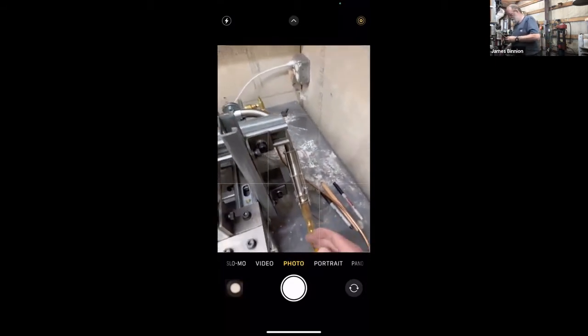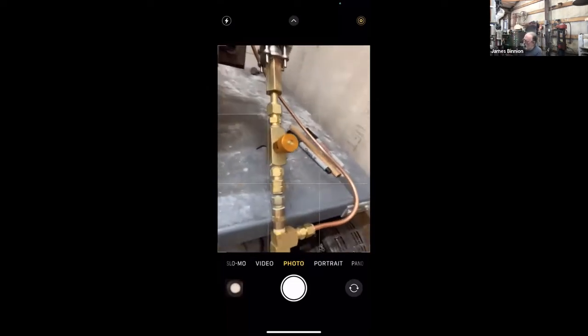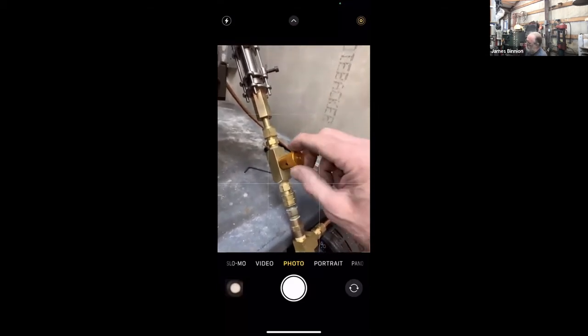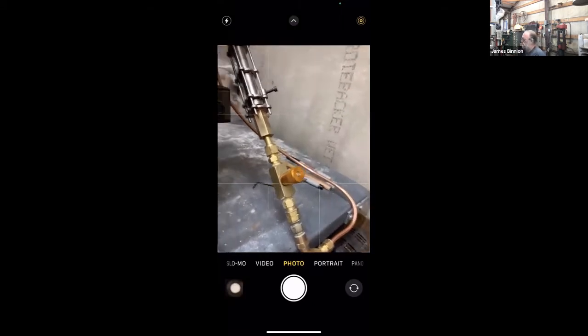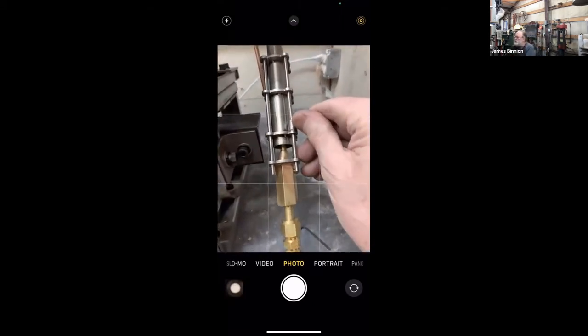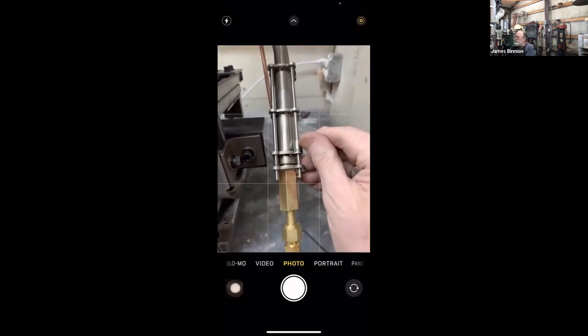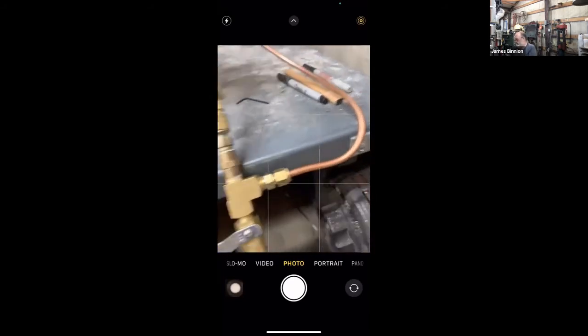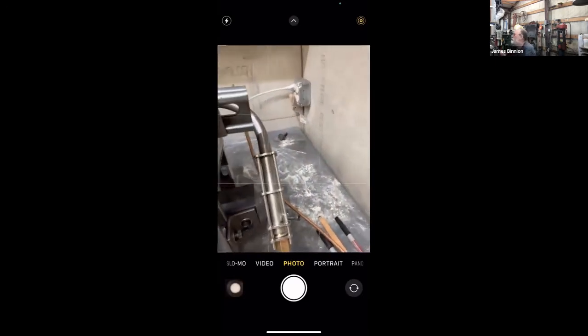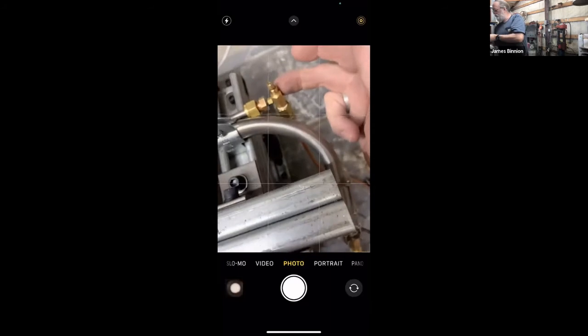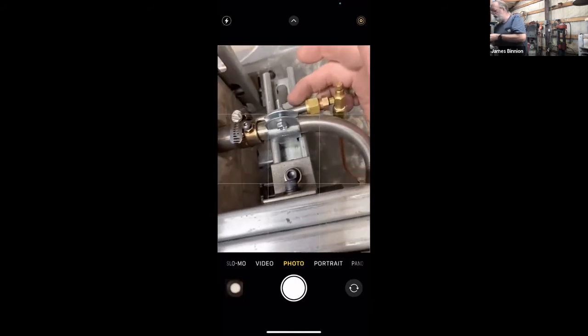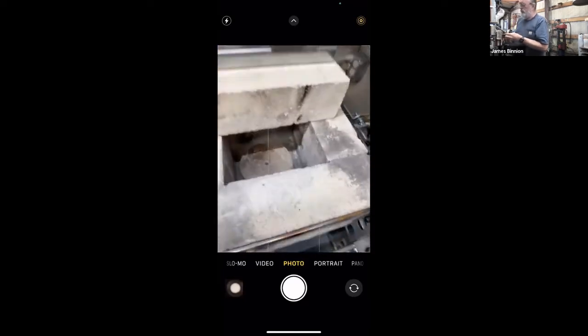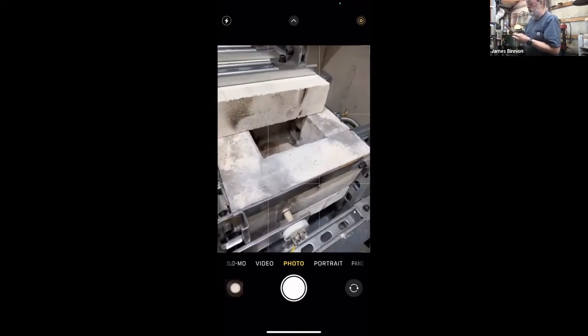And to try and get that really fine control, this is a 10-turn needle valve. So as you turn it out, it gives you very fine control over the amount of gas that's flowing in. The shutter allows you to control the air. And then I've got a T connector coming off here, going up again to a little needle valve, and then just a straight pipe that's bringing the raw propane in for the added reduction.